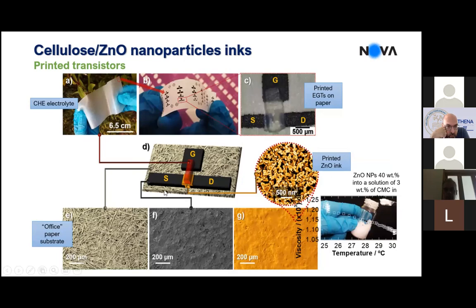But you see here the paper, and the paper coated with the nanoparticles, and you see the nanoparticles layer that was printed. You see, that is not, of course, a full continuous layer, or full dense layer. It's made of nanoparticles with 100 nanometers in average in diameter. But it's enough to create a percolative path. Nevertheless, you have some nanopores in the layer.